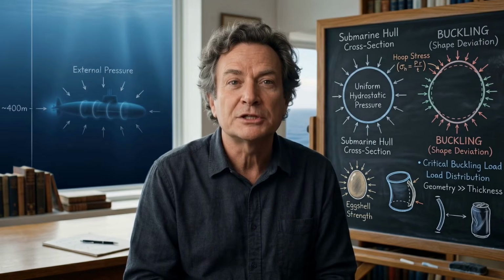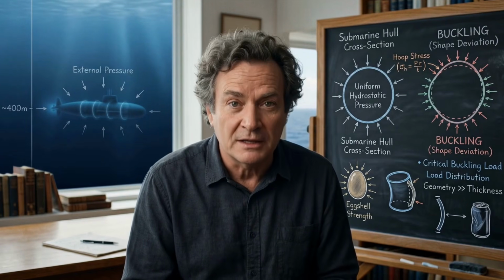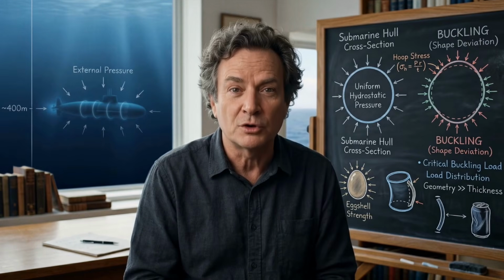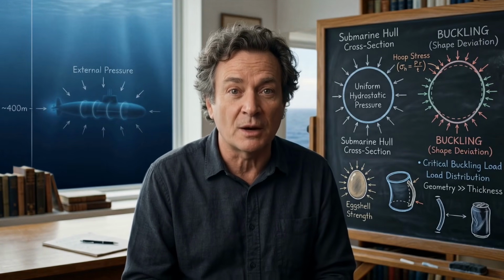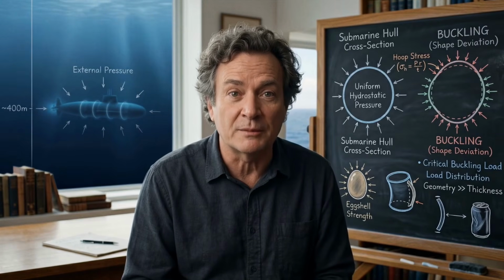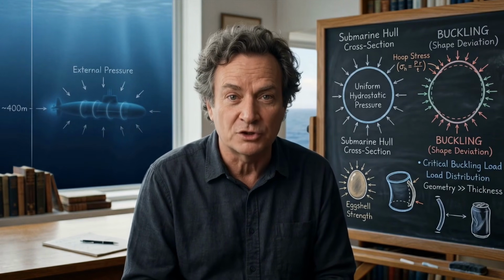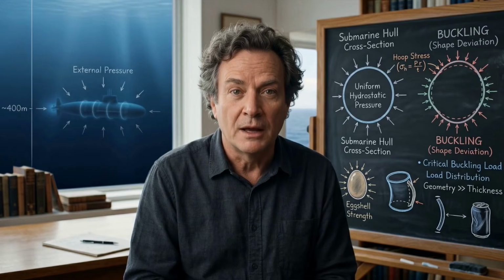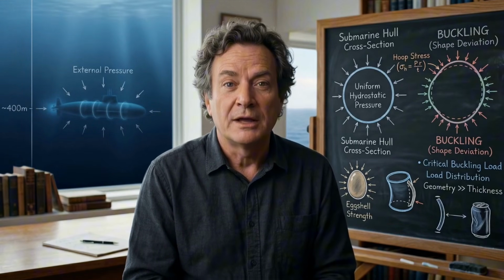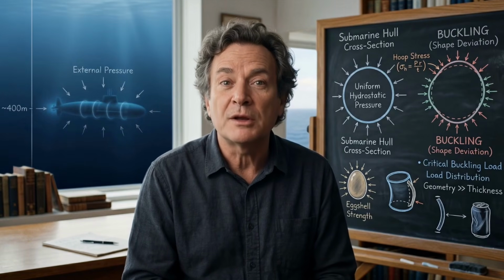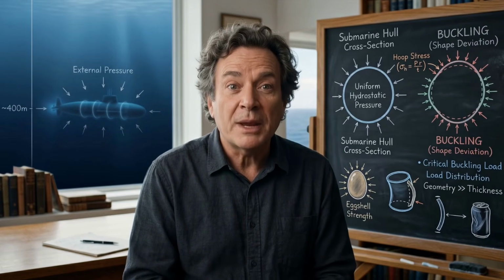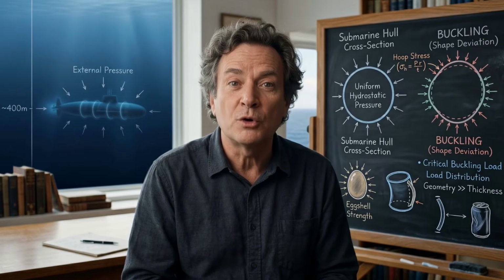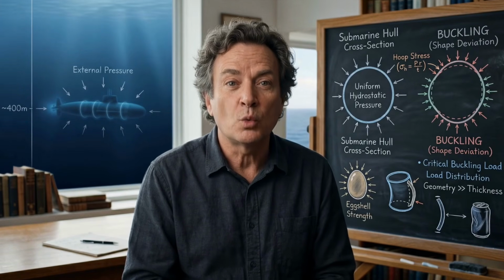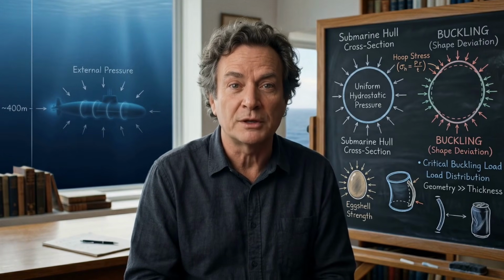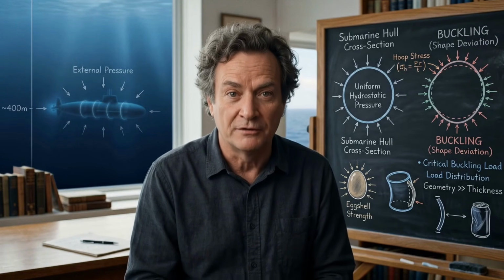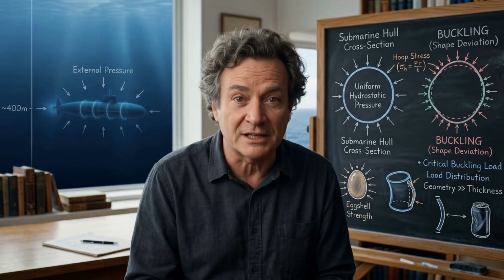What Euler found is this: the load at which buckling occurs depends not primarily on the strength of the material, but on the stiffness of the material and the geometry, specifically on something called the second moment of area, which is a way of describing how the cross-sectional shape resists bending. And the critical thing is that this critical load scales with the inverse square of the length. Make your column twice as long, your critical buckling load drops to a quarter, not to half, to a quarter. The geometry is more powerful than the material. A shorter, stubbier column can carry far more load than a longer, slimmer one made of exactly the same steel.